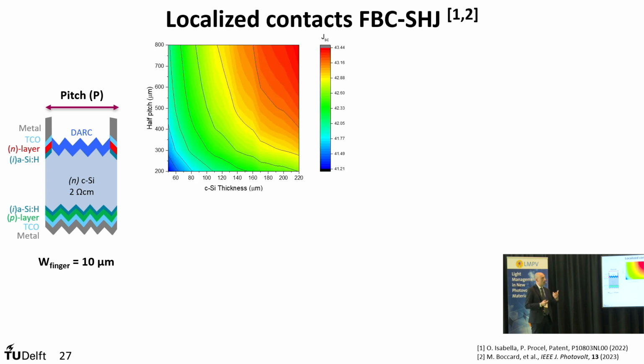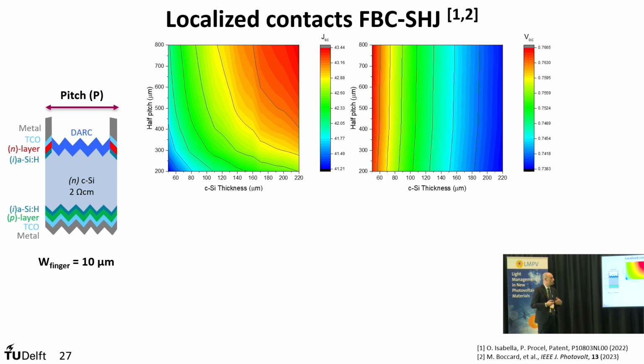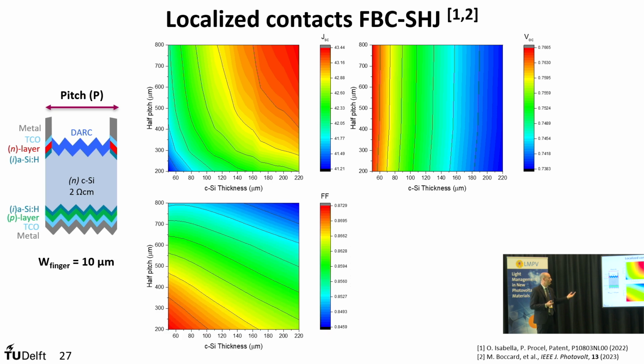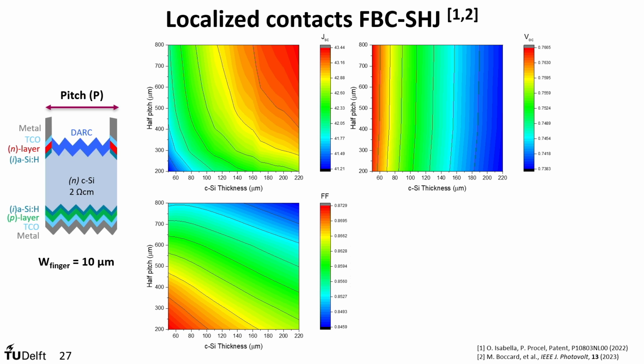And what we do, we run different crystalline silicon thicknesses versus different pitches. And of course, as expected, the larger the pitch, the more light you let into the wafer. So the top right corner is where the JSC of the device would be optimized. Then you have the VOC, which is largely independent in this case from the pitch. It only depends on the thickness of the wafer. And then the fill factor gives essentially the opposite behavior over here, where for thinner wafers and the smaller pitch, you can get better, of course, collection.